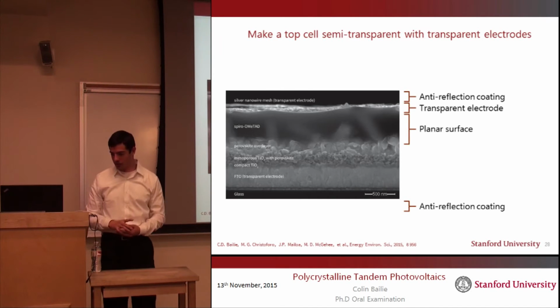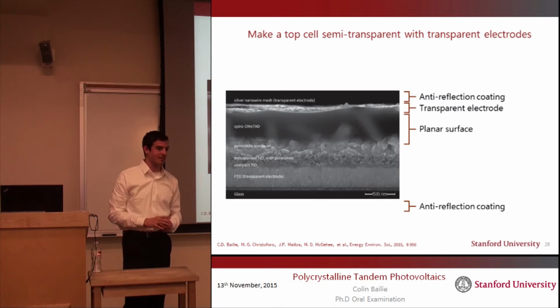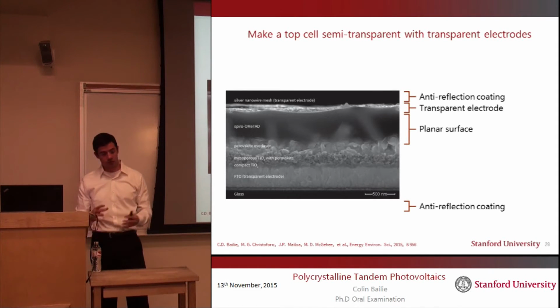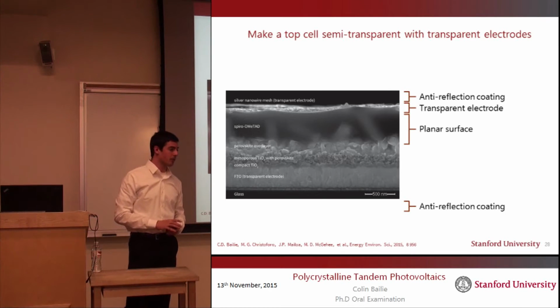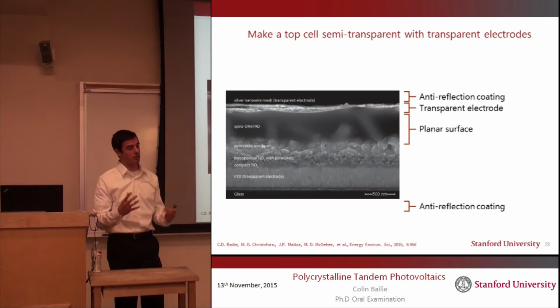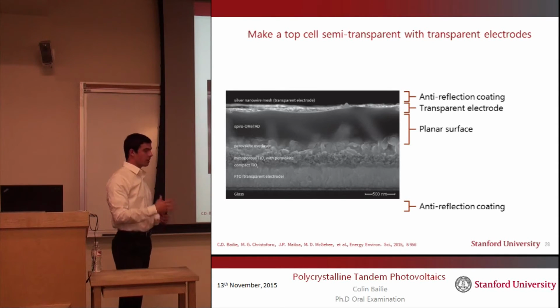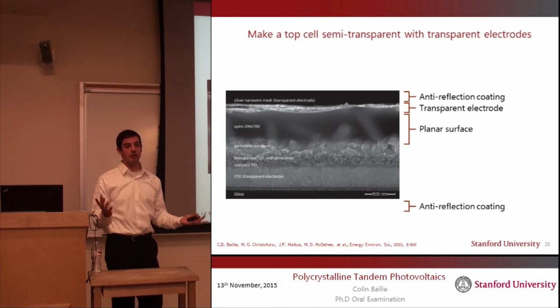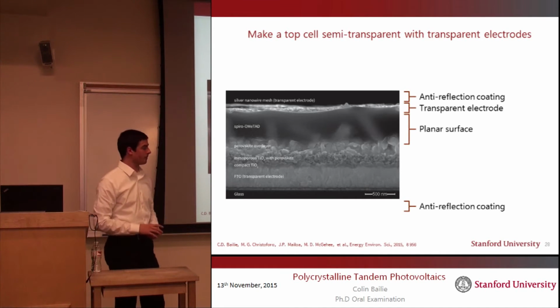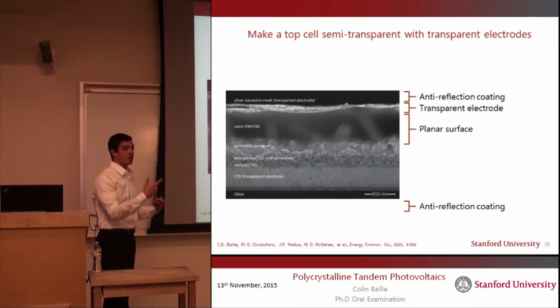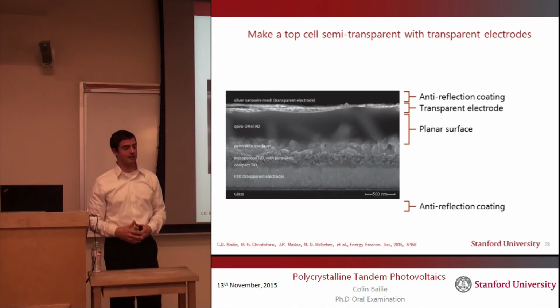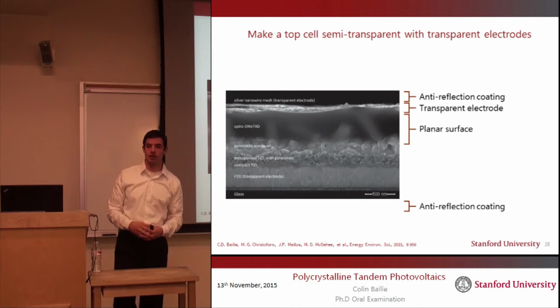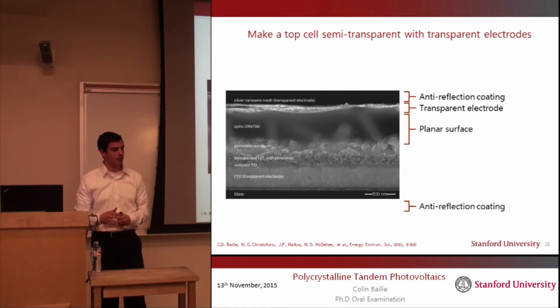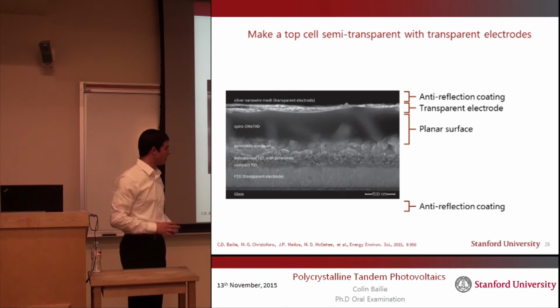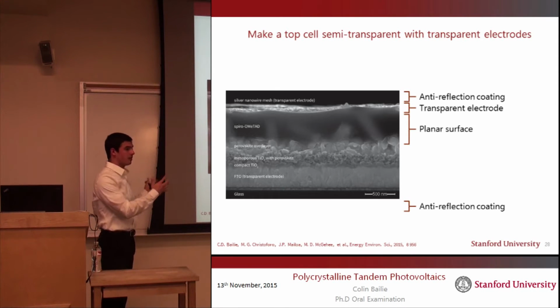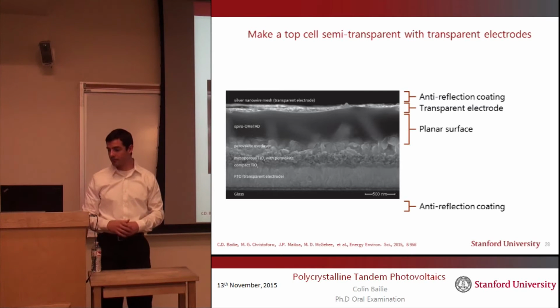And this is particularly difficult because the perovskite has a number of design challenges that you have to work around. First, because it has an organic molecule, if you leave the perovskite exposed and you heat it up to a moderate temperature, about 60 degrees C, given enough time, the organic will simply evaporate from your system and you won't have perovskite anymore. Another problem is that because the perovskite is made of salts and you solution deposited it, if you are not careful about the layers that you are solution depositing on top, if they're made of the wrong solvents or if they have water and are wet, then the perovskite can either be dissolved or undergo degradation.